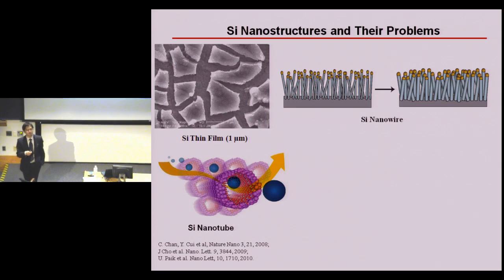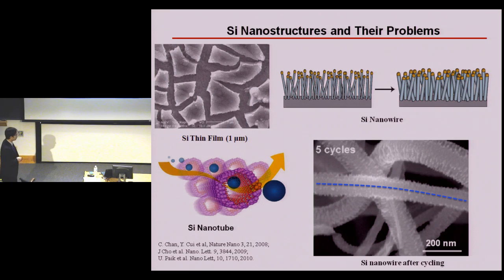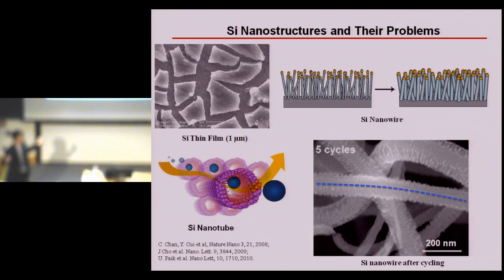So there are two things in common for this kind of silicon-based structure. One is that all these structures are based on nanomaterials. That means the stress building up in this kind of nanostructure is much smaller compared with the bulk silicon material. The second is that this kind of structure has a lot of open space for the silicon to expand. For example, here you have a lot of space between the silicon nanowires. That will allow silicon to expand in different directions. But there's still a huge problem associated with this kind of freestanding silicon nanostructure. For silicon nanowires, after a few cycles, we still find that they tend to break because there's nothing to support these one-dimensional objects.